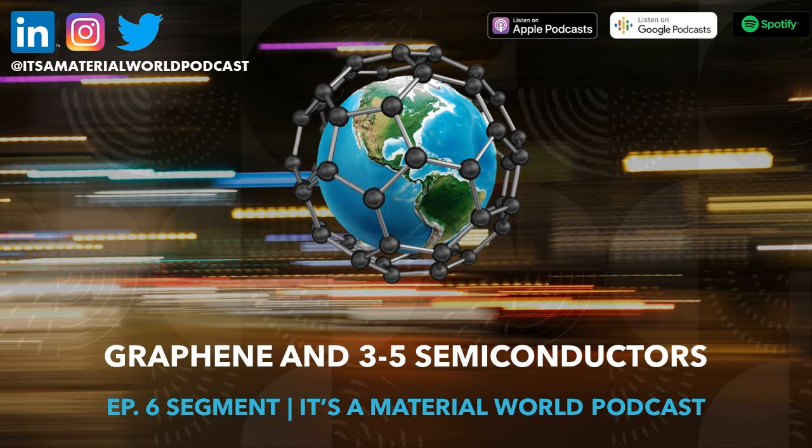But manufacturers are dealing with challenges where they get multiple layers. They've got so many layers and they're all entangled. We need one layer stacked neatly over the other for it to give the final properties. And that's not happening. That's where manufacturers are getting into two-dimensional processes. They say there are certain nano CVD-like processes where 90% of graphene can be a single layer.